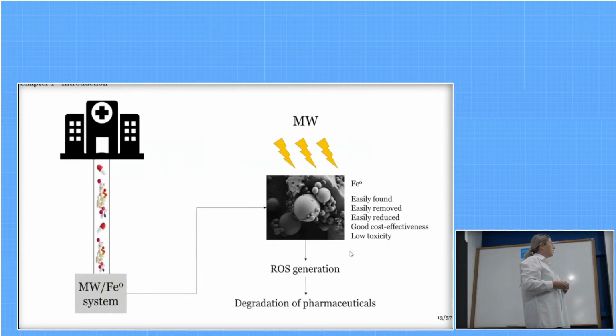In this research, we collected wastewater samples in a local hospital in the northern region of Rio Grande do Sul, and we employed the microwave zero-valent iron system for the degradation after screening, and we chose zero-valent iron because it is easily found, it is easy to remove through co-precipitation, easy to reduce it, it has good cost effectiveness, and it has low toxicity. It is also known that zero-valent iron can promote ROS generation under microwave, and we tested this to know the viability for the degradation of the real sample.